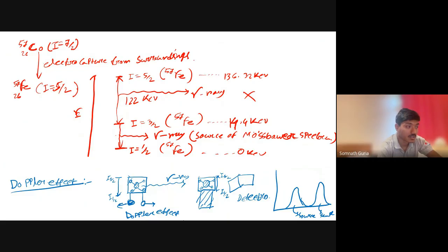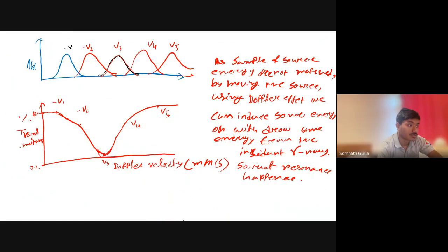And then that 3/2 state decays by emitting a gamma ray, which is required for the iron 57 excitation from I equals 1/2 in our sample. With respect to the Doppler effect, we get the spectrum by moving the source, providing some energy or taking energy out of the source, and providing that particular gamma ray energy to the sample, which absorbs it. We will get a curve, that is the transmission curve.